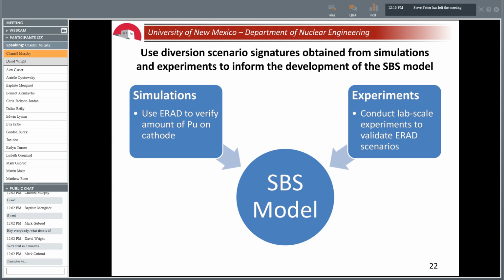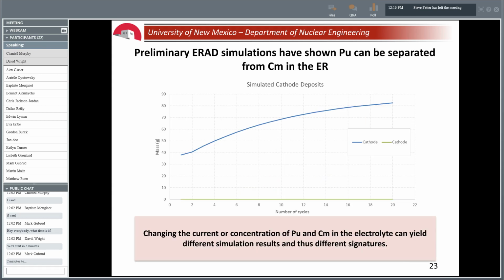The ERAD simulations were done for a simulated Korean Advanced Pyroprocessing Facility under an operating cycle of 20 days. And it showed that plutonium can be separated from curium. In this graph, the blue line shows the amount of plutonium deposited at the cathode. I've lost some information here on the graph. Plutonium was deposited, about 80 grams after 20 days of operating, but curium did not deposit with it.